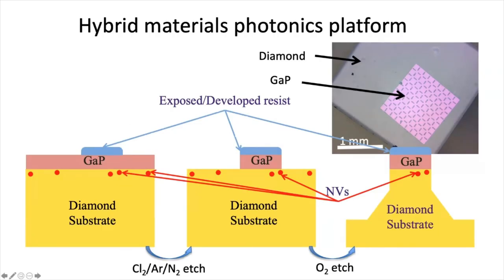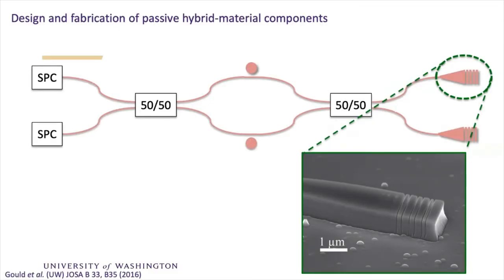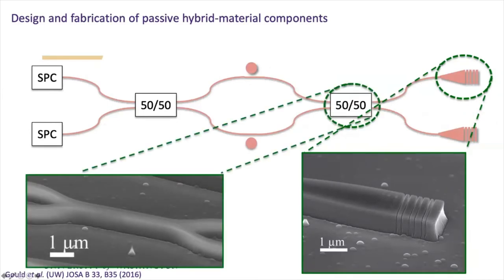And so the type of platform that I work on is I like to separate out the defect layer from the photonics layer. And so my particular platform, I work with gallium phosphide on diamond, and I create photonics using nanofabrication techniques, and they're created on a diamond substrate, where I've also created these nitrogen vacancy centers in diamond. So this is an example of the types of structures that you can make. If you look here, this little line here is separating out the gallium phosphide from the diamond, and these are couplers, so the photon comes down this waveguide and then can shoot up to our microscope.